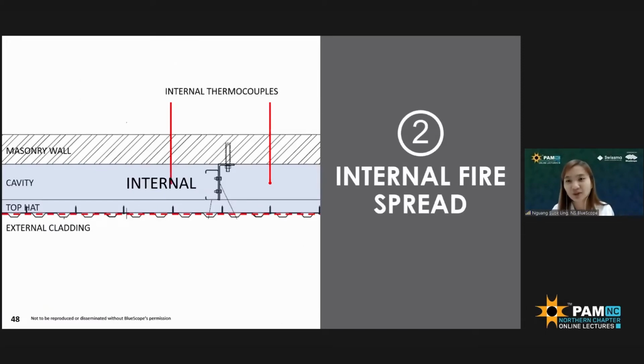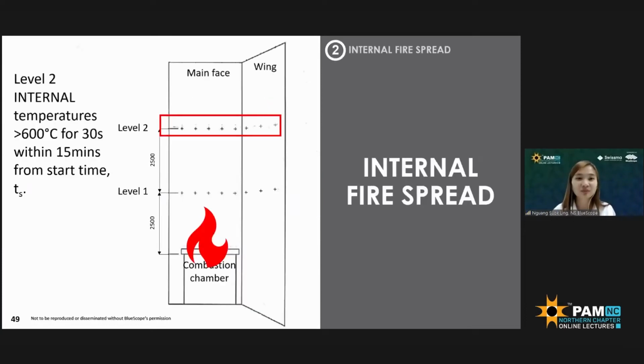And the second criteria is internal fire spread. The criteria is pretty similar to the first criteria, but the second is mainly on internal fire spread. So it is also measured based on the level 2 internal thermocouples, as shown in this figure here. In order for the cladding to pass, the internal thermocouples at level 2 should not have a continuous reading of more than 600 degrees C for 30 seconds within 15 minutes from the start. It's pretty similar to the first criteria.